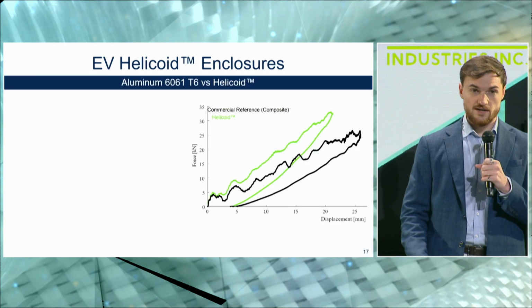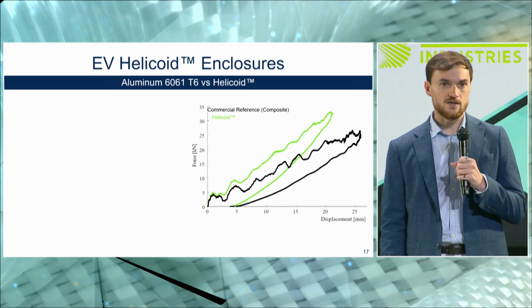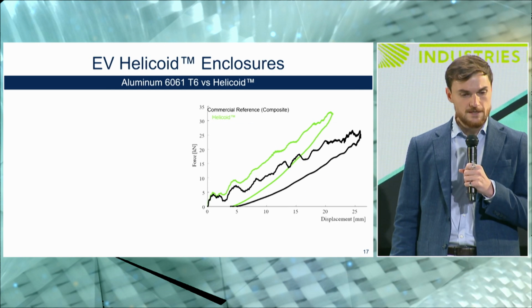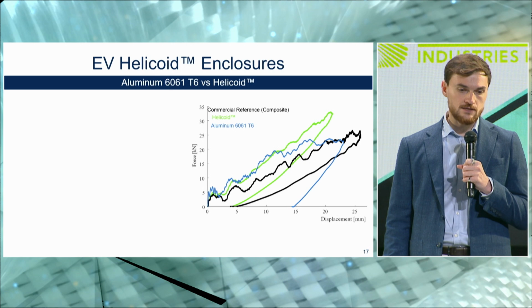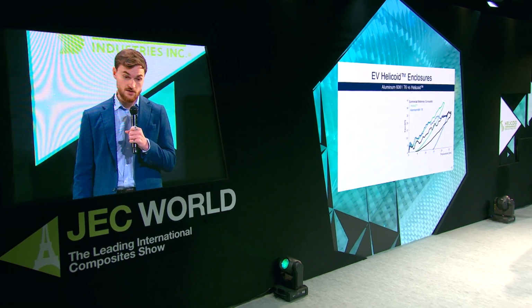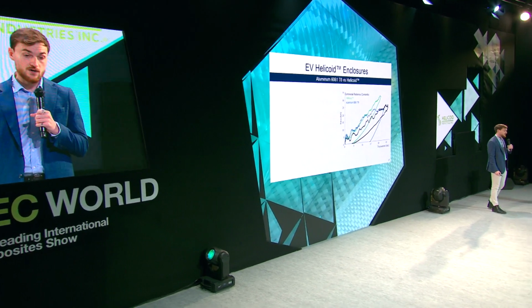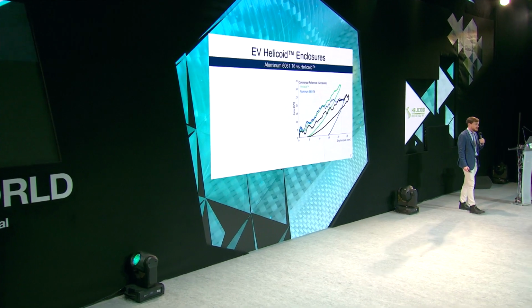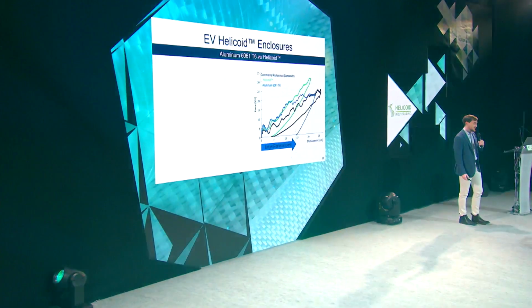We also did compare against the real commercial reference, which is the aluminum. And again, the benefits are very high. Once again, we are able to deliver much higher load-bearing capability, but more importantly, in this case, we have a much lower permanent deformation in the plate.